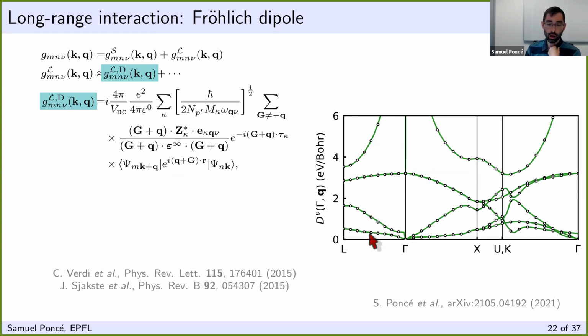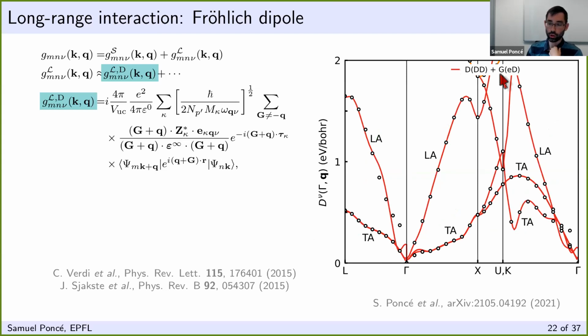And so now the issue is this discontinuity. If I zoom in on this deformation potential, I'm now showing what you get. You do recover the 1 over Q divergence, but what you can see is that we don't interpolate correctly these non-analyticities when going towards gamma. Here, what I'm showing is when we approximate this long range with only the dipole term. We've subtracted and added back the dipole at the dynamical matrix level and at the electron-phonon matrix element level.